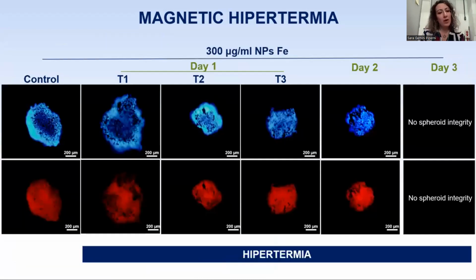And after 24 hours of exposition, we applied cumulative magnetic hyperthermia cycles. So we applied 3 cycles on day 1 and an additional cycle on day 2. And we observed a considerably progressive reduction in spheroid size. After an additional hyperthermia cycle in the 3D spheroid on the 3rd day, spheroids are completely disintegrated.